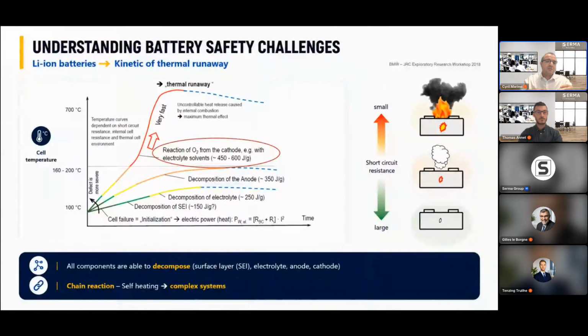In fact, you have more and more small mechanisms. You start with a failure mechanism inside the cell that initiates the internal short circuit. Then this creates a first heat, and this heat will decompose the passivation layer, this SEI layer on the anode, which will also create heat itself.